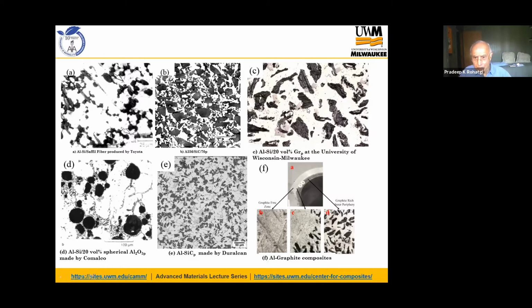But by introducing graphite particles into the melt of aluminum, we have been able to produce this particulate composite microstructure, and I will talk to you about this later, how it has been used to reduce friction and conserve energy and environment. Another example where spherical alumina particles have been dispersed in aluminum matrix. Here is another example. 20 volume percentage of this angular silicon carbide are dispersed in aluminum, and I will show you this has been used for brake rotors in many cars to conserve energy and fuel.